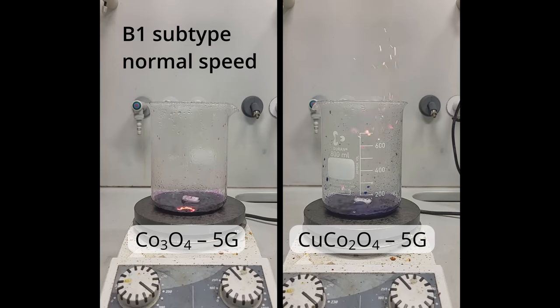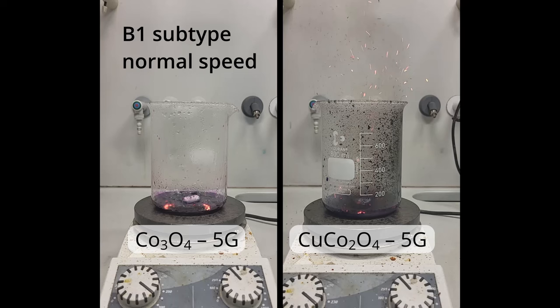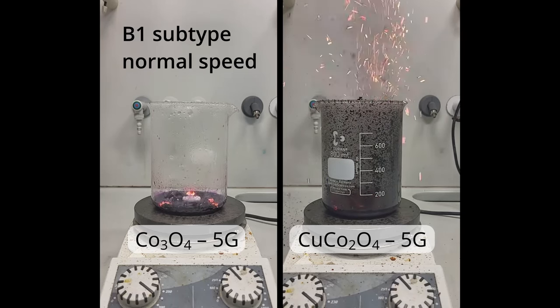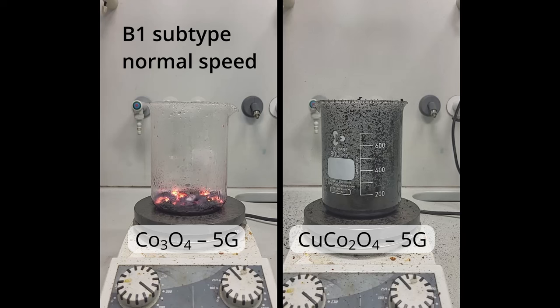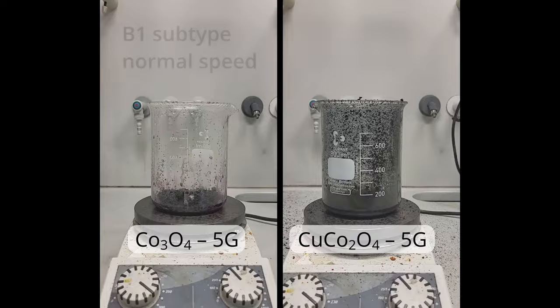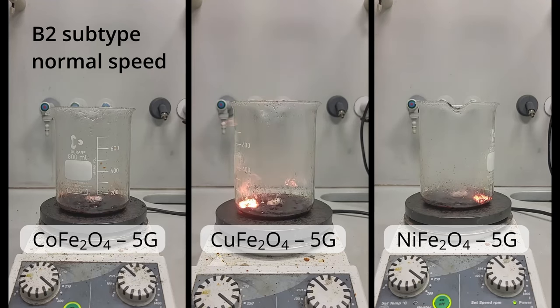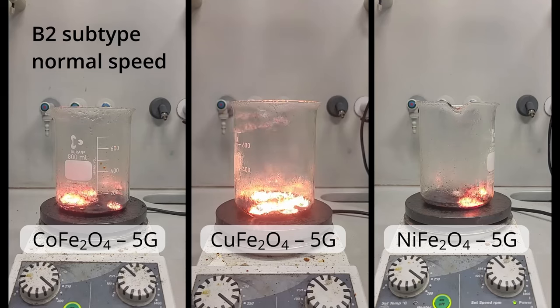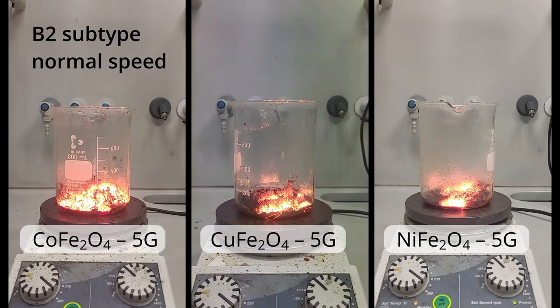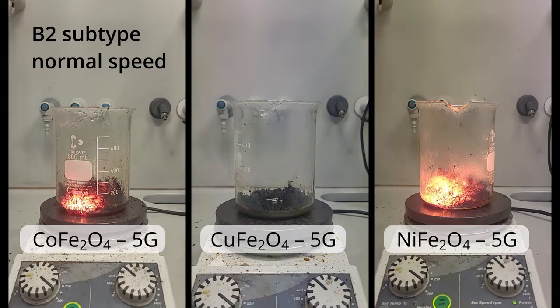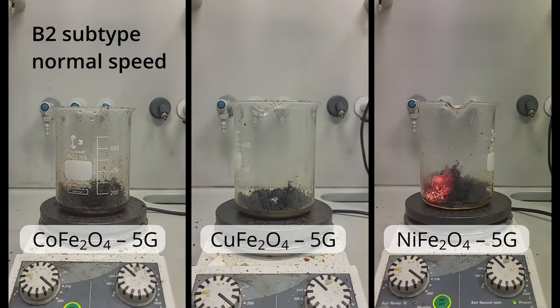We call the B-type combustion the dense. The B1 subtype combustion happens when a high loading of glycine is used, hence the temperature reached is very high, and in the combustion process you form lava and you produce very dense chunks of material. In the B2 subtype combustion, we also use a very high loading of glycine, hence we form again lava and we produce dense structure.